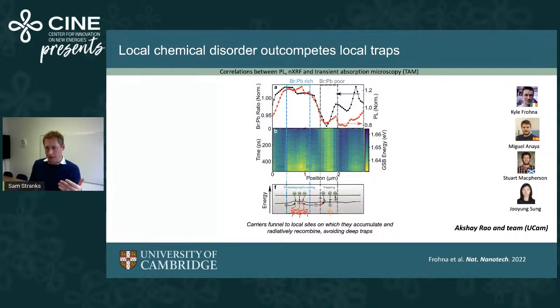So this is actually visualizing this photodoping that I showed earlier, where we have an accumulation of many of these carriers. Because they've got a very high density of carriers, we get very high radiative efficiencies. An important point here is that these holes that move about, because of these funnels, instead of hitting traps, can be more likely to funnel into these radiative sites rather than into these non-radiative sites. We believe this is one of the reasons why these alloyed films are working very well in solar cells, because of this serendipitous energetic funnel from a heterogeneity or a distribution of halide chemistry.